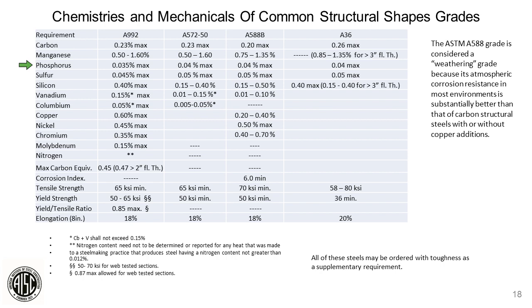If you look at sulfur here, same thing with 992. It's a lower sulfur. It's done intentionally to help the properties of steel, especially Charpy V-notch. And then A572-50, 05 max. So those aren't added. Those are residual. We try to minimize those in our processing.